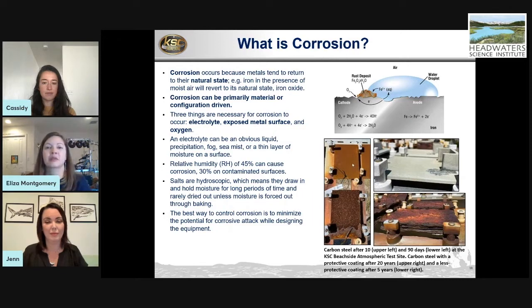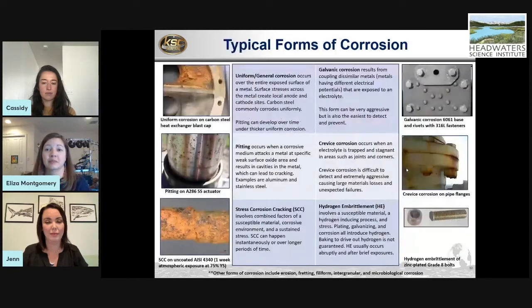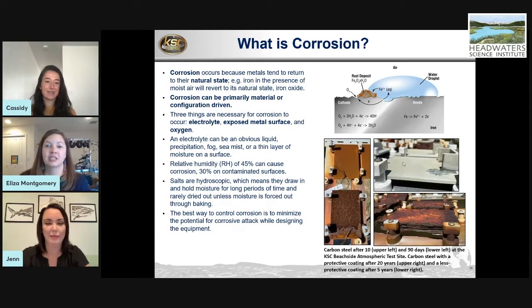This is a panel that would have started out pristine, and after 10 days, it's already started to corrode. After 90 days, it's very corroded. This top picture shows a panel that has been out for 20 years, and it looks perfect. So this is something that's been out for 5 years and is already what's called corroding or exfoliating. Exfoliating would be like lots of tiny little layers. And so this is what 5 years would do. In 20 years, you wouldn't even see this anymore. It would be back in the ground.